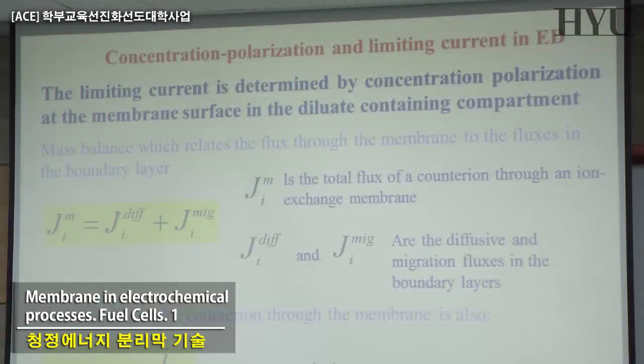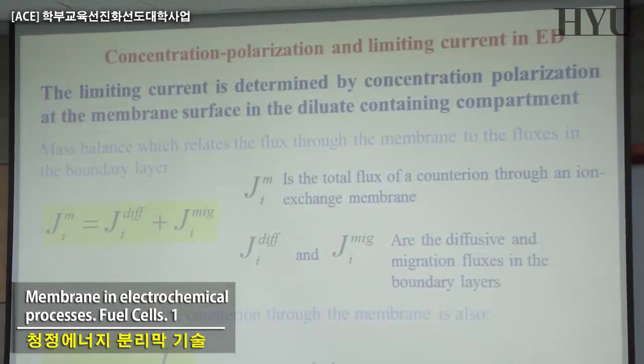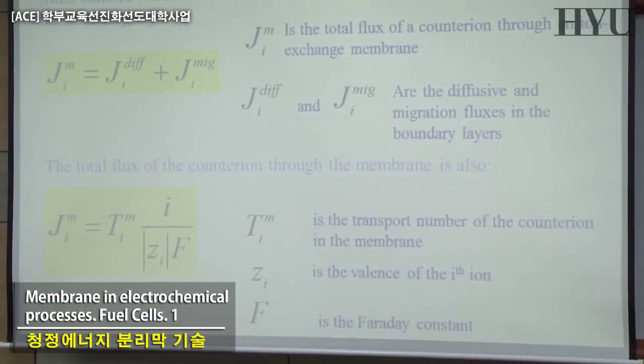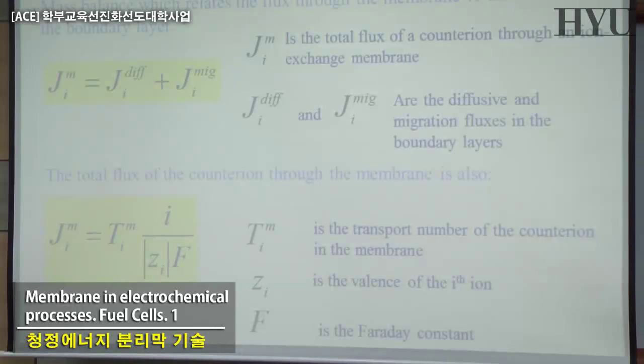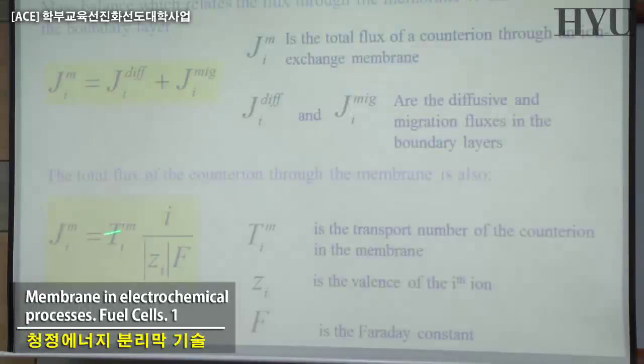There is an infinite resistance, basically, if there is no ion that makes the cross flow. And for doing this, we will use exactly the same kind of approach, the theory of this interfacial stagnation layer, to calculate just this kind of current. So the transmembrane flux of your ions in the membrane phase is given by the diffusion plus the migration, and this is diffusion and migration flux within the boundary layers, and the total flux can also be defined in this way. There's one number here that I don't know if you are familiar with, that in this case you will utilize very often, which is called transport numbers.